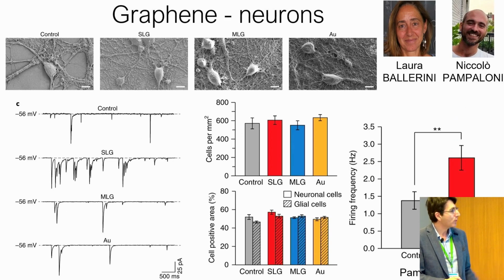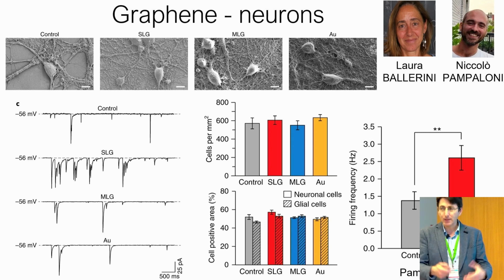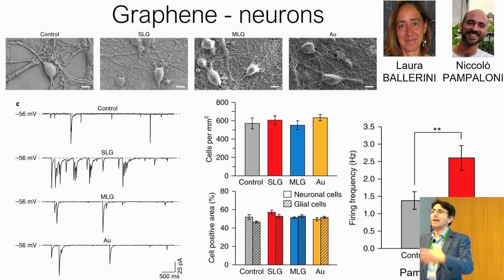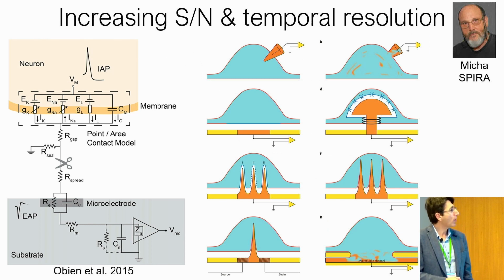I'm not entering into the details with other work done with Laura Ballerini using graphene, another carbon-based material, where we observed that this material, which is considered for novel electronics, also resulted in a boosting, in an enhancement for single-layer graphene of synaptic activity, synaptic release, and network activity. So overall, the idea is increasing the signal-to-noise ratio for accessing the subthreshold activity. And for the moment, I didn't give you any result for that. And it's actually turned out to be very, very challenging.